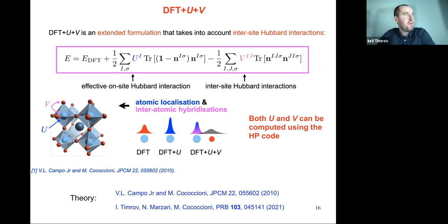But it is important to remember that we should not take hybrid functionals as a reference, because hybrid functionals are also approximate. You have a fraction of exact exchange, which is 25% in PBE0 and HSE06. But hybrid functionals also fail in solids because this fraction of exact exchange is not proper, not correct. So there are more advanced hybrid functionals. They're called dielectric dependent, developed in the group of Giulia Galli in Chicago and other works by Kronik and other groups.